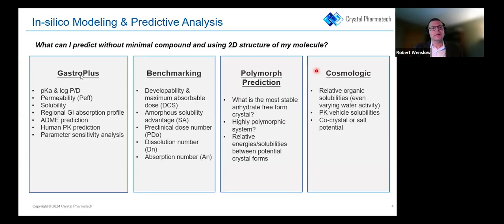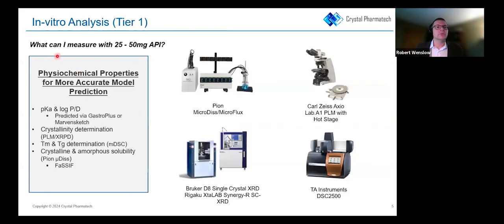More recently, we've been implementing it to crystallize new forms. So you get this predicted polymorph landscape. How are you going to crystallize those forms? Cosmologic can actually give us some insight into that. So what is this tier one? What are these tools? With 25 to 50 milligrams of material, the first thing we want to do is get something that's crystalline. We want an understanding of the amorphous phase, which you can quickly get with a modulated DSC, getting a glass transition, and then seeing if you could even do a polymorph experiment at high heating above the glass transition temperature to see if it's going to crystallize.